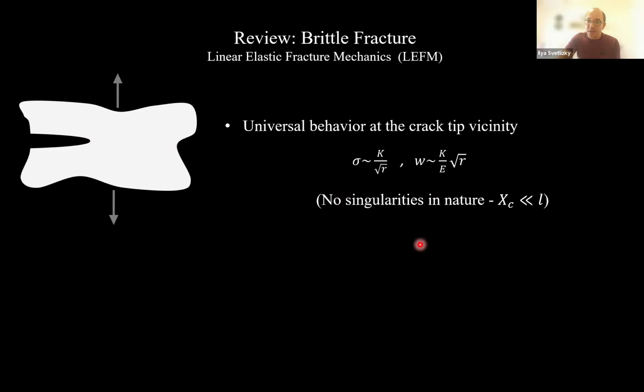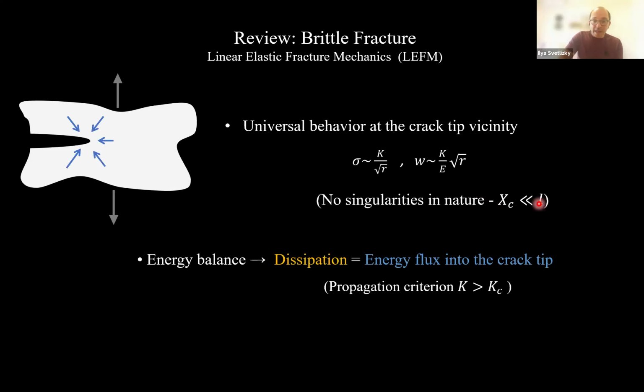Now, in nature, there are no singularities. So obviously, the very high stresses around the tip are regularized at some region, usually called the cohesive zone or the process zone. The brittle theory describes cracks where this length scale of the process zone is much smaller than any other dimensions of your system. The only dissipation takes place at the crack tip. All the elastic energy that goes into the crack tip is dissipated there.